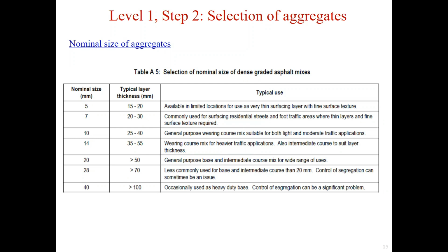A guide to selection of layer thickness and nominal size is shown in the table here. For example, if the nominal size of the dense graded asphalt mix is 40 millimeter, then the layer thickness has to be greater than 100 millimeter.